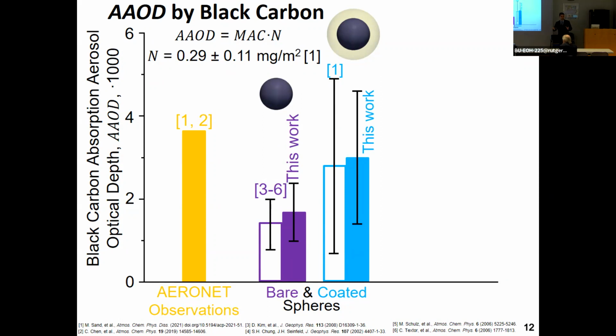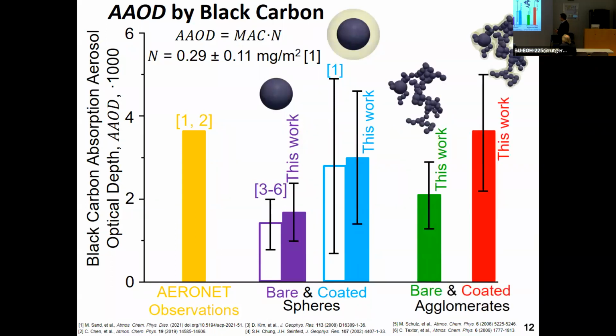So this tells us that the procedure that we follow in general is correct, but we still underestimate the observed absorption aerosol optical depth that is provided by the AERONET network of sun spectrometers. So when we actually estimate the total light absorption for bare as well as for coated agglomerates, we see that, of course, the total light absorption increases by 20 to 30%. And now you can see over here that the absorption aerosol optical depth that we obtained for coated black carbon agglomerates is exactly on point with the observations. So this tells us that we can take this total light absorption of black carbon that accounts for the realistic morphology of these nanoparticles, and introduce it to a real climate model to have a better quantification of its contribution to global warming.